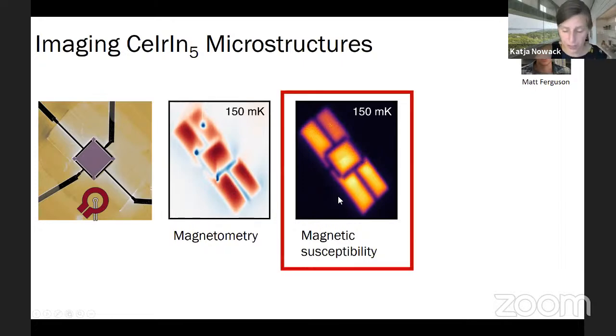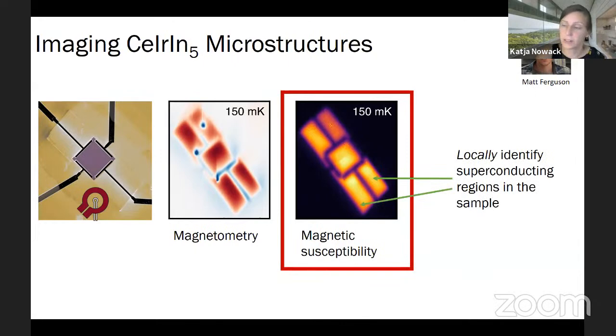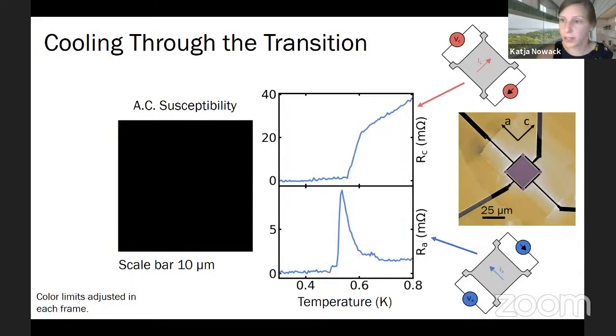But we're really interested in this imaging mode, and we simply use it in this experiment to locally identify where the sample is superconducting and where it is not. Everything where you see bright color tells us that the sample is superconducting. Everywhere you see dark or black, the sample is not superconducting. So here we're outside the sample, of course, but you can also see the trenches that were cut into the sample using the focused ion beam. All right, so now we're ready to watch a movie.